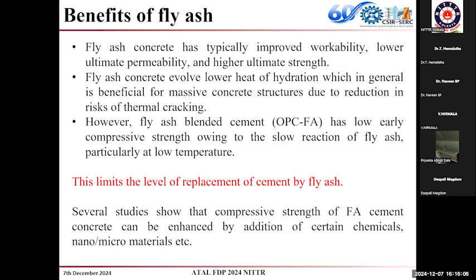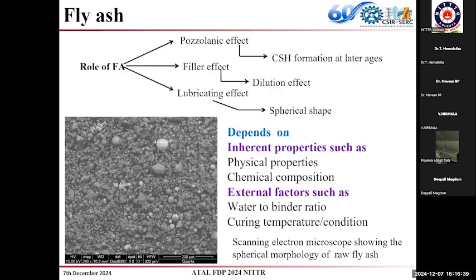So many things can be avoided, like thermal shrinkage and cracks, by using fly ash as an ingredient. As I mentioned, the code has mentioned a replacement level of up to 35%, but nowadays there is a lot of research, and at CSIR-SERC also we have research to see what happens if we go beyond 35%, and if strength is reducing, how that can be compensated. We want to use beyond 35% of fly ash, so that kind of studies we have also attempted.